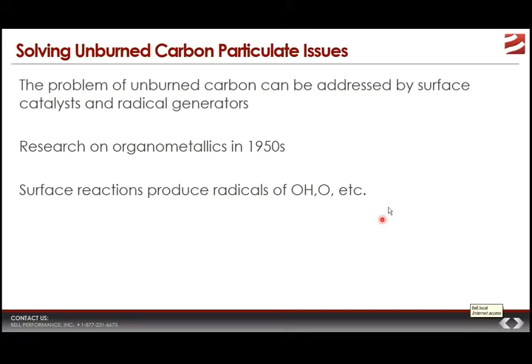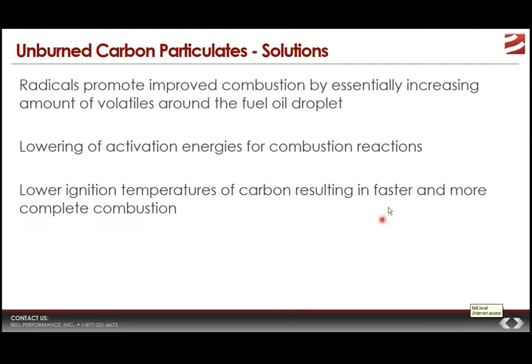Well, there's a number of ways that they do it. One of the ways, without getting overly technical, is that they help produce more radicals, more OH molecules, more single oxygen molecules. These radicals are extremely reactive, and they will want to participate in more combustion reactions. So what research showed is that these organometallics improve combustion essentially by acting on the fuel oil droplet and increasing the amount of burnable or volatile components that come out of the fuel oil at any given time.